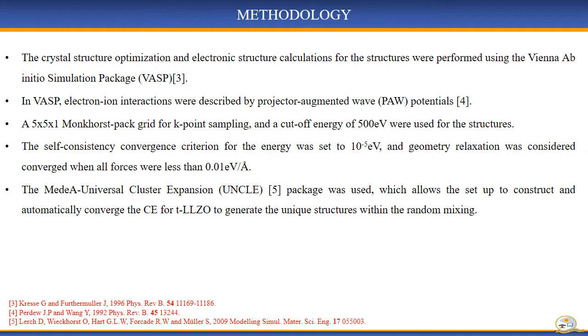The Vienna Ab Initio Simulation Package (VASP) was used to perform the crystal structure optimization and electronic structure calculations. In VASP, the projector augmented wave potentials were used to describe the electron-ion interactions, whereby a 5x5x1 Monkhorst-pack grid and a cut-off energy of 500 electron volts were used for the structures.